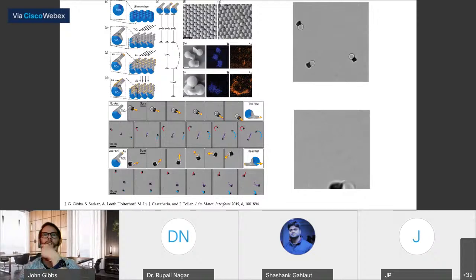Okay, so the one with the gold on the side was a little bit less interesting. We got some rotational motion primarily. I was expecting this to be a little bit more active because the interface between the two materials is larger for the one where you have gold on the side. However, it seemed to kind of make them stall out a little bit, which is not entirely clear why that occurred at this moment still.